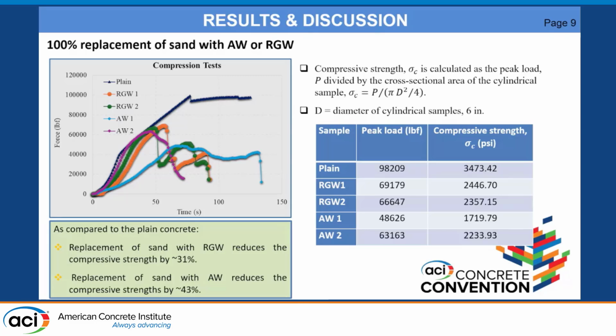And again, a sort of similar story with the compressive strength. This was around a 3,000, 3,500 PSI mix plain. You can see the plain samples right around 3,500. With the recycled glass, we got to about 2,400 on average. And again, with the alumina waste, there was a bit of a gap there, with one sample being 1,700, the other being about 2,200. So again, overall, recycled glass reduced the compressive strength by about 31%, and alumina waste by about 43%.